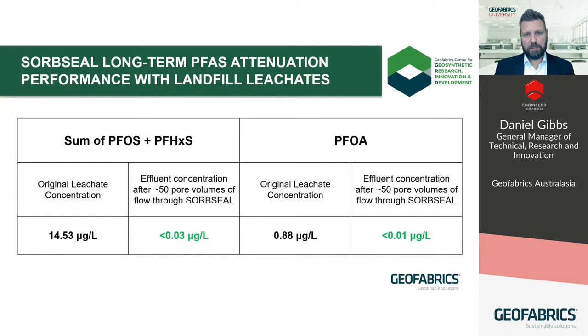This means that in the landfill base liner and cap, where pore volumes through the GCL are likely to pass through more slowly due to either increased confinement and or a lower hydraulic head potential, and the fact that leachate generation slows down dramatically post-closure, Sorbseal may very well continue to provide attenuation of PFAS both during the operational phase and for many years post-closure, even beyond the moment leachate stops being generated.